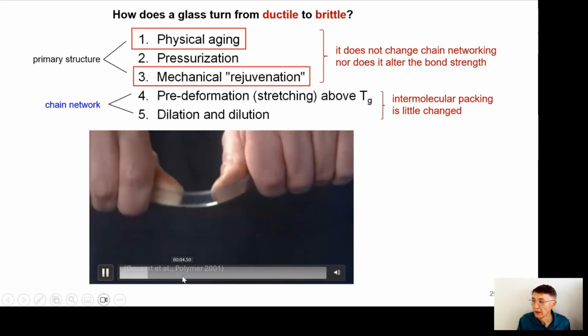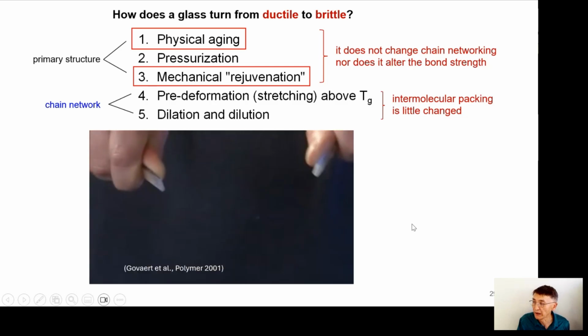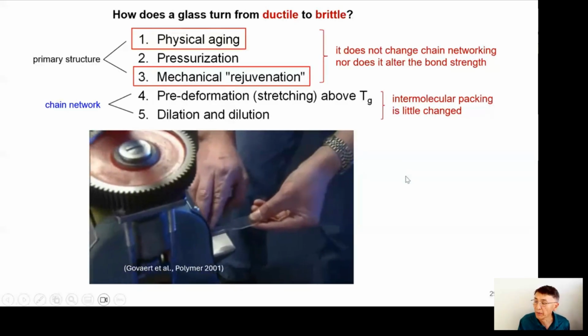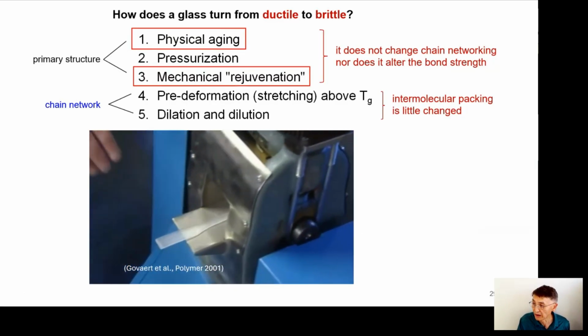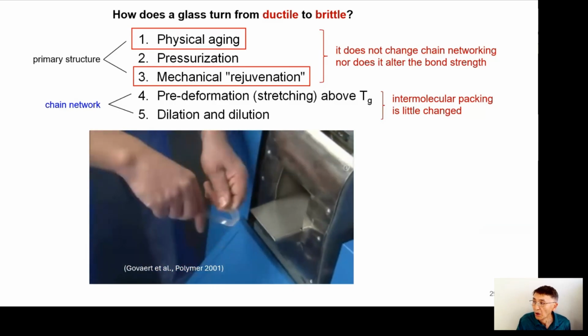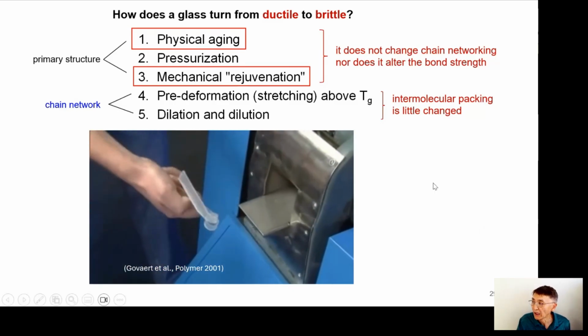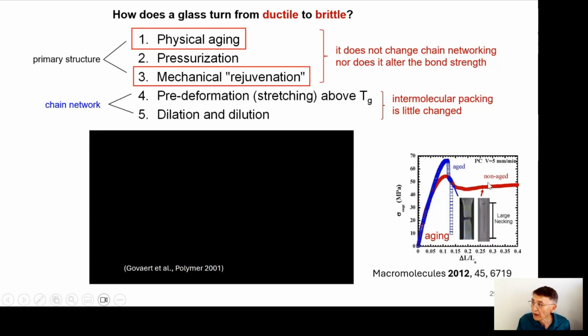And this movie from Eindhoven shows how it happens. This brittle polystyrene, after going through a two-roll mill, turns ductile. Beyond that, we know even the ductile polycarbonate turns brittle upon aging. So that's the aging. So you can see these are three factors that influence the brittle-ductile transition.